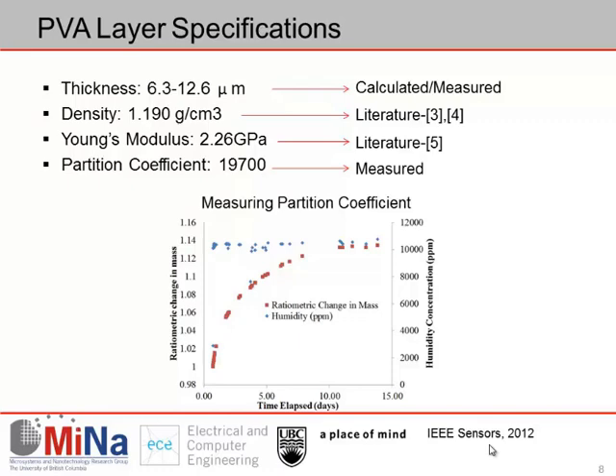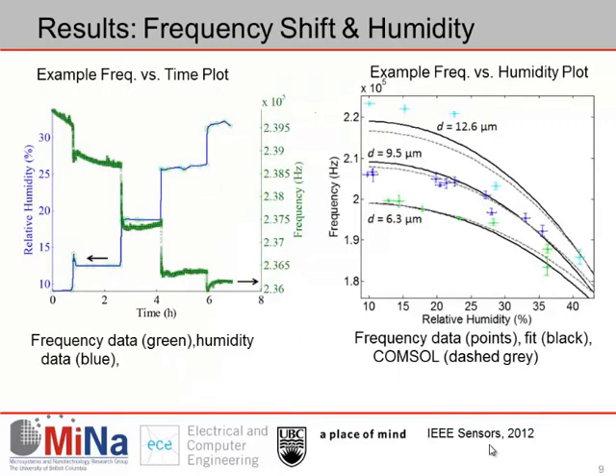So this plot here shows how we went about measuring the partition coefficient of our PVA sample. We simply exposed a sample of PVA to a constant relative humidity over a long period of time, measured its mass change, and used that to calculate the partition coefficient. Okay, so now that we have values to compare those which we are trying to obtain through fitting, we can look at our results. Now these are the sort of plots that we get.